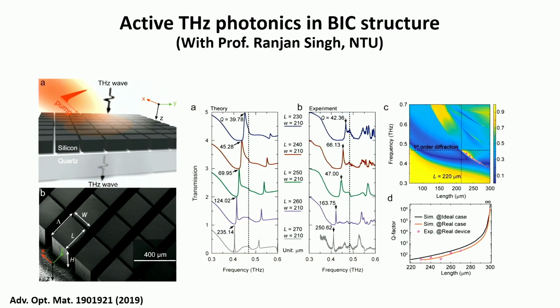Right. So another area in metamaterials which is still popular is active metamaterials. Can we control actively tunable response from these metamaterials? So here, this is silicon discs on top of quartz. By an incident optical pump beam, we can control the refractive index and thus the response of these metamaterials or metasurfaces at the terahertz frequencies. So that's what has been shown. We can control the Q factor, and we can control the transmission through these structures in the terahertz range.